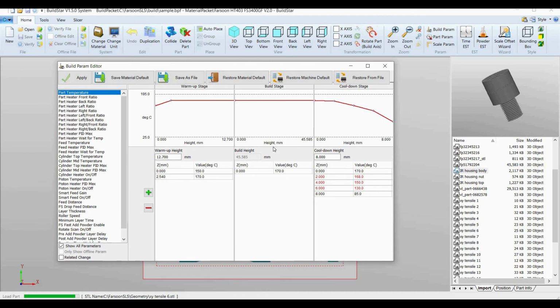Next, we have part temperature. This is used primarily if you see curling or orange peel throughout the whole build. Usually the build temperature is too low. So we can go into build temperature and we can raise the part bed temperature as a whole. Or inversely, we can raise the duty cycle, which will decrease the time it takes for all of the heaters to warm up to that set point.